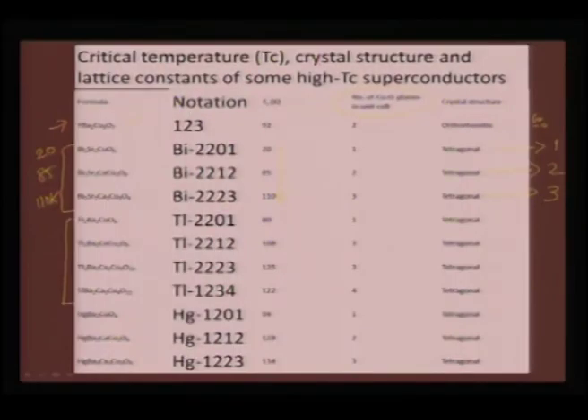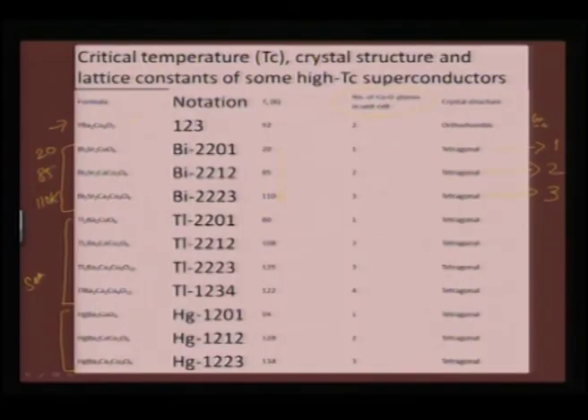3 copper oxygen planes. Another group of compounds that has really attracted interest is thallium based cuprates and mercury based cuprates. As you can see, the maximum has been achieved for mercury based cuprates, which show a Tc of 134 K. The main problem with bismuth, thallium and mercury is that they really evaporate. Therefore, you can end up with a non-stoichiometric or chemically non-homogeneous compound. So, most of the reactions here are done in sealed tube conditions, and that imposes a problem of making this in bulk, and that is why yttrium barium copper oxide is still preferred for practical application, because you do not have stringent requirements in terms of synthesizing it.